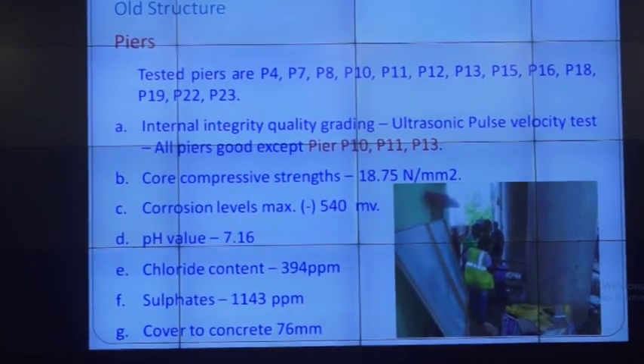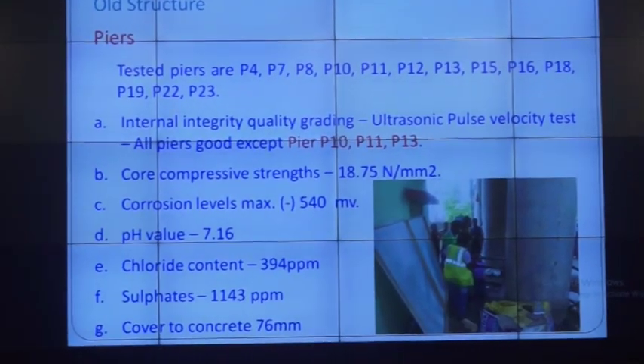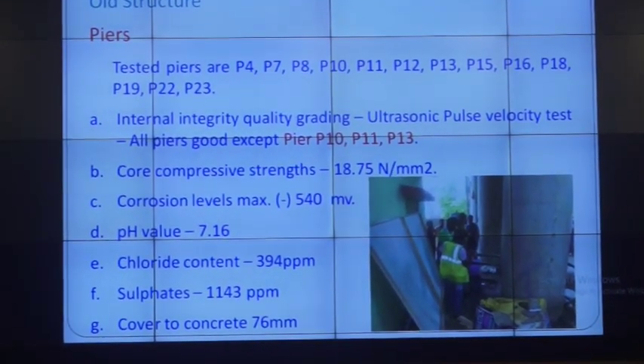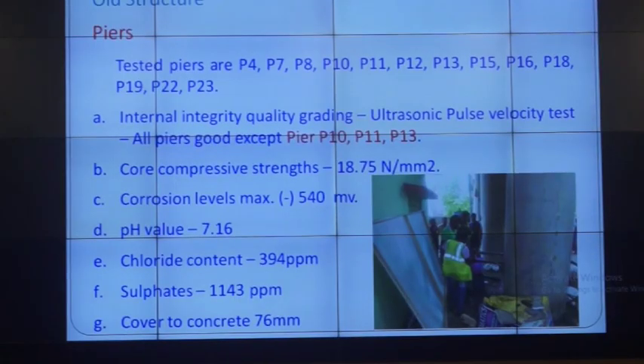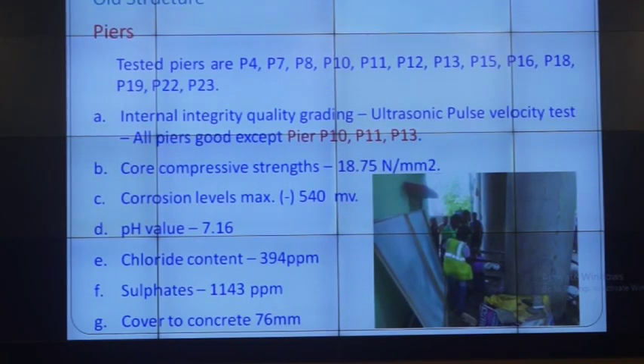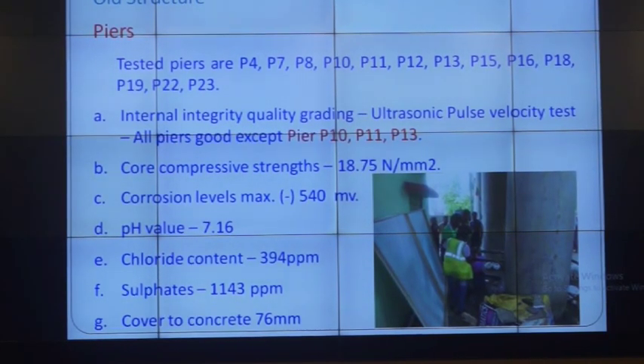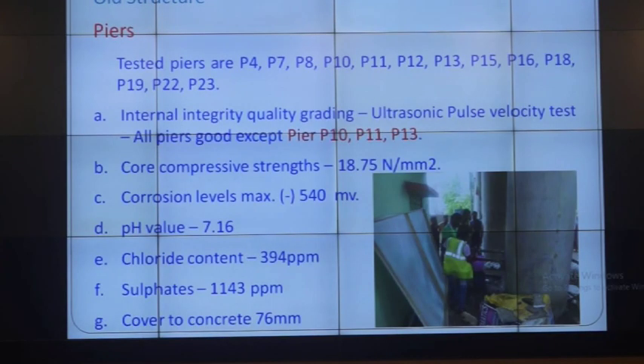The chloride content is about 394 ppm, by and large okay, because chloride content is related to the quantum of cement you put into the concrete. Sulfates are also similar, quite low, because our code allows higher quantities. Cover to the concrete is very good, 76 mm. More cover also is not good because you get cracks at the bottom very easily. If it's about 40-50 mm, it's okay, manageable.